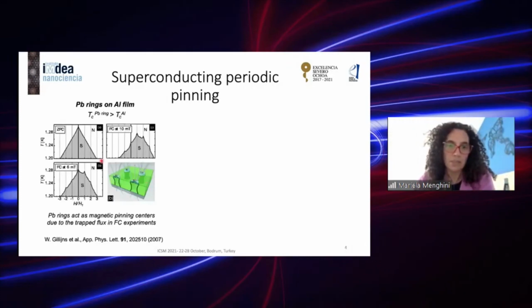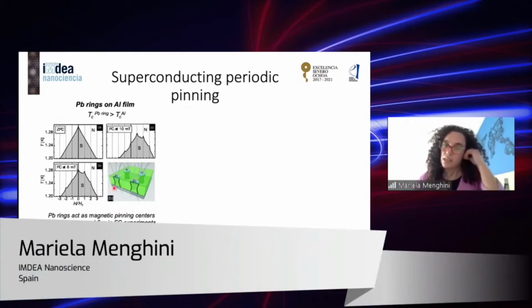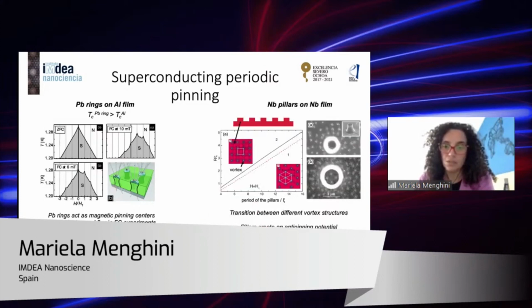There has been some previous work on this topic. This is work from Gillijns et al. some time ago, where they looked into an array of lead rings deposited on top of superconducting aluminium, and they see that these rings can act as magnetic pinning centers due to the flux that is trapped within the rings. Later on, there is work from the group of Irina Grigorieva, where they looked at the vortex structures in nanopillars of niobium on a niobium film. Basically it's a niobium film that is carved with these pillars.